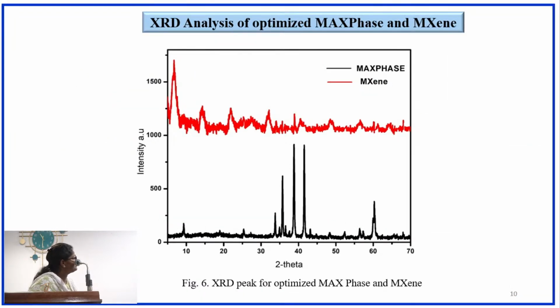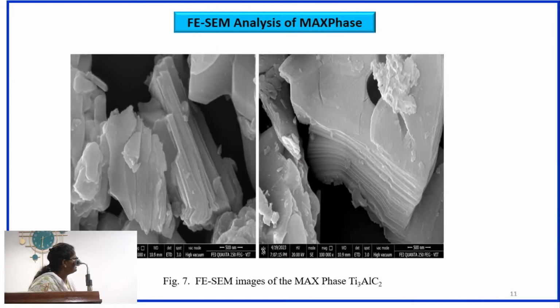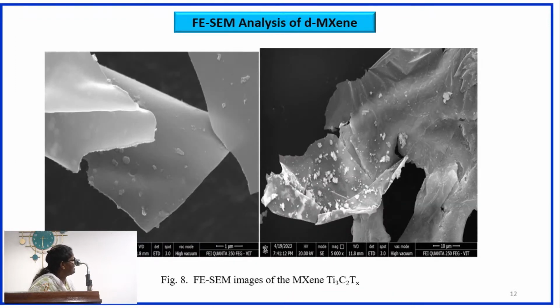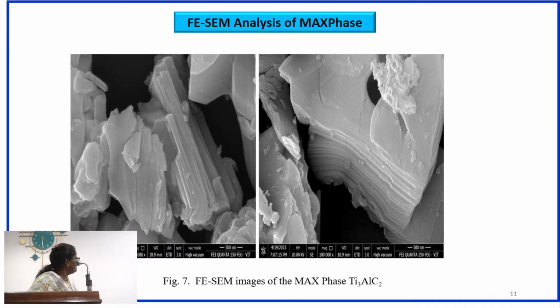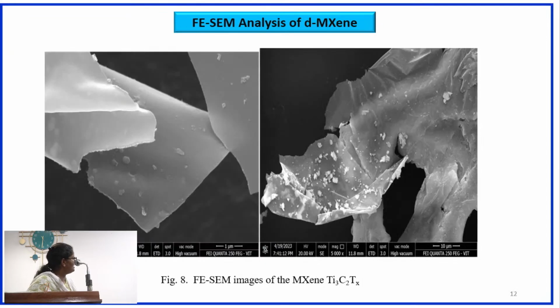This is the optimized MAX phase and MXene. On MXene formation, the 002 plane shifted to a lower angle, which implies a layered structure. This is the FESEM analysis of the MAX phase, and this is the FESEM analysis of delaminated MXene. The bunch of MAX phase, after electrochemical etching, shows single sheets.